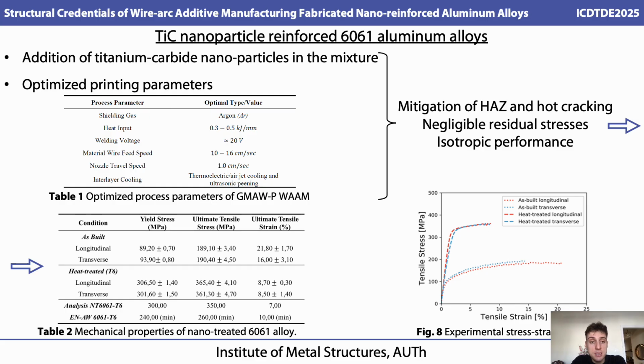The welding voltage should be around 20 volts, and the material wire feed should be somewhere around 15 centimeters per second. Additionally, the nozzle travel speed should not exceed 1 centimeter per second, while for interlayer cooling we propose thermoelectric air jet cooling and ultrasonic pinning. Through these proposed printing parameters and with the addition of titanium carbide nanoparticles in the mixture of the aluminum alloys, we consider that the heat affected zones, hot cracking phenomena, the residual stresses, and the anisotropy regarding the mechanical properties are significantly mitigated.